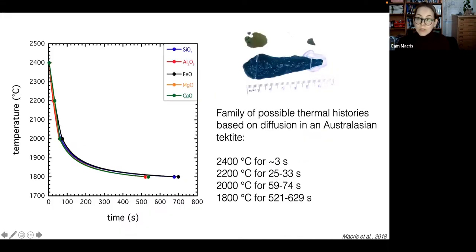But what we can do is use this diffusion behavior in experiments to come up with a family of possible thermal histories for a sample, which is what is shown in this figure here. Each of these curves is plotting the diffusivities for one of these oxides, and they all lie on top of each other, as we expect based on what I just showed you.